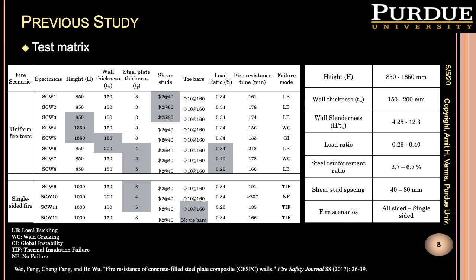This is the test matrix of the study conducted by Wei et al. that was published in 2017. What you'll notice from this test matrix is that there were about 8 specimens that were subjected to uniform fire tests. And there were about 4 specimens that were subjected to one-sided fire tests. Generally, the wall thicknesses were in the range of about 150 millimeters, which is about 6 inches, to 200 millimeters, which is about 8 inches.